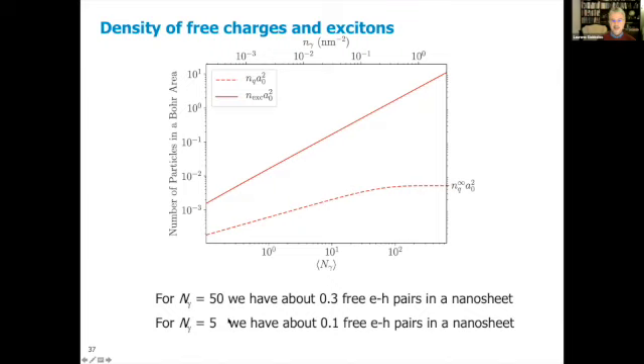And what you clearly see is that it increases sublinearly. If you go from 5 to 50, you could say, okay, then I get 10 times as many free electron-hole pairs, but it is less because of the bimolecular electron-hole recombination that gives a bias towards the excitons.